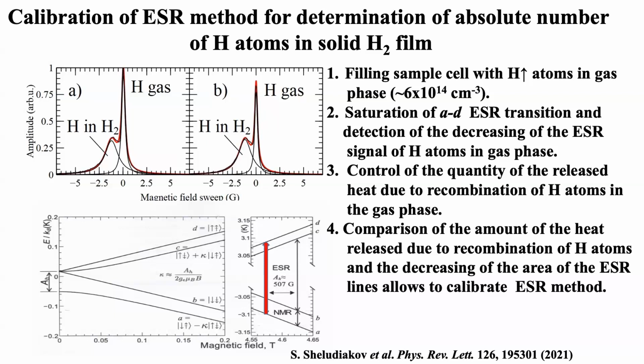We know that in each act of recombination, 4.5 electron volts is released. So after this process, we also measure the signal from the gas line, and we can know the change of the area, and how much heat was released during recombination. We can calibrate the number of atoms against the area of this signal, so we know exactly how many atoms correspond to this area.